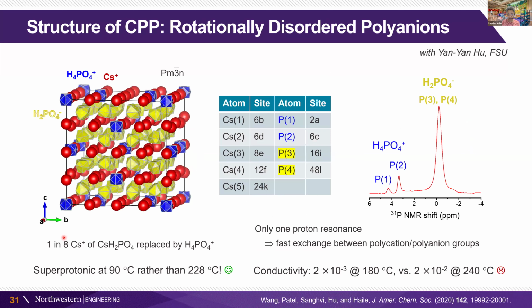We then grew, my very amazing student grew this compound at high temperature above that transition that happens at 90 degrees Celsius, pulled it out of the aqueous solution and ran it over to the single crystal diffractometer and made sure that it stayed hot during the X-ray measurement, and then was able to solve the structure. And we can see the superstructure arrangement where 1 in 8 of the cesium cations is replaced by effectively an H4PO4 positive cation.